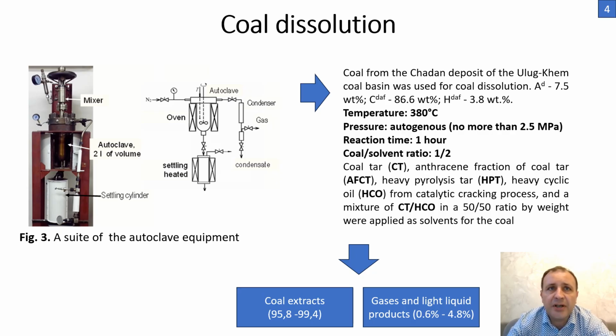Coal tar, anthracene fraction of coal tar, heavy pyrolysis tar, heavy cyclic oil from a catalytic cracker unit, and a mixture of coal tar and heavy catalytic oil in a 50-50 ratio by weight were applied as solvents for the coal. After preparing the paste, we placed it in an autoclave and heated at 380 degrees Celsius for 1 hour under autogenous pressure. As a result, we received coal extracts and not more than 5% of gases and liquid products.